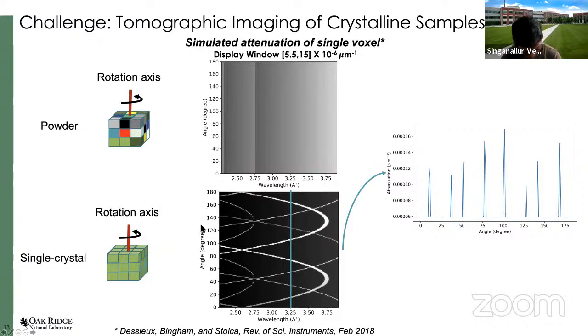So here is a single voxel. Think about a single piece of a material that you're imaging through in transmission, and you're measuring the attenuation coefficient as a function of wavelength and the rotation angle. So typically, in standard CT, when you rotate an object, the linear attenuation coefficient of the voxel does not change as a function of rotation angle, right? So that's one of the foundational assumptions. However, when you have a single crystal material, that is not true.